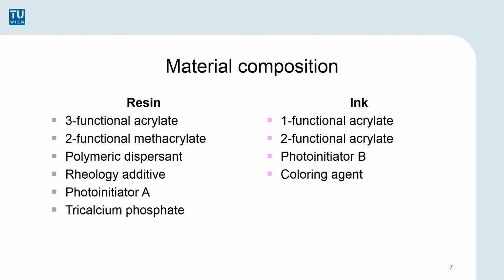The ink, on the other hand, is composed of a low viscosity acrylate, a cross-linking agent, a photoinitiator, and a red coloring agent. This composition leads to a very soft and compliant material.